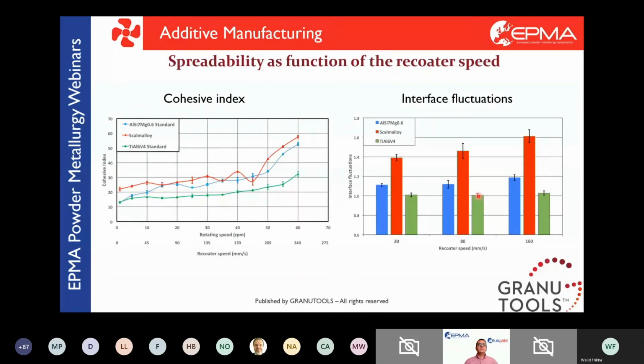So here on the left side for the cohesive index, we have the cohesive index versus the rotating speed. And here we even put the recoater speed, so we have a link between the recoater speed and the rotating speed. Now this link is not to be taken too seriously, this is something that is approximative. It will give you a range, an idea on what the linear speeds will be, but it's not 100% accurate.